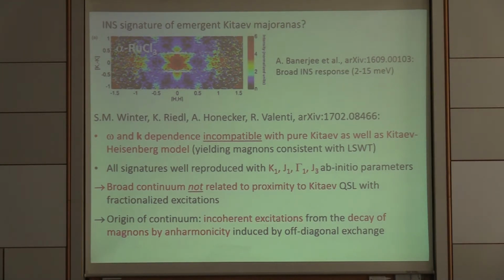And they also showed that when you reduce these disturbing terms like gamma1, J3, and J1 and continuously evolve the parameters towards the Kitaev spin liquid, the inelastic neutron scattering pattern drastically changes. So all that led them to conclude that what is found is actually not related to the proximity of the Kitaev quantum spin liquid. Rather, it seems that this broad continuum of incoherent excitations is due to the decay of magnons by the strong anharmonicity. And this decay is mainly driven by these off-diagonal, highly anisotropic exchange interactions. So they strongly reduce the lifetime of the magnons, and that causes these inelastic signatures found in the neutron scattering.